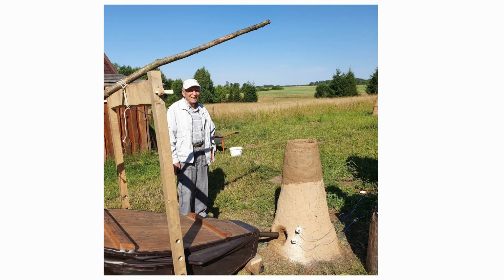We also removed the tuyere, creating a 10 centimeter diameter hole to simulate natural air supply. During this trial, the burden residence time nearly doubled, averaging 25 minutes. Unfortunately, the strategy failed, yielding no iron production, just a small amount of slag and a significant quantity of unburned charcoal and under-reduced ore.